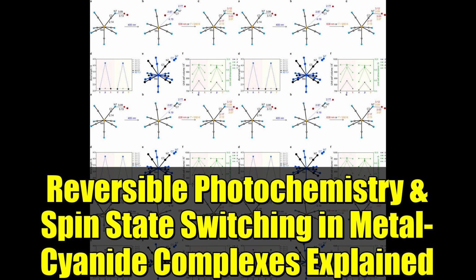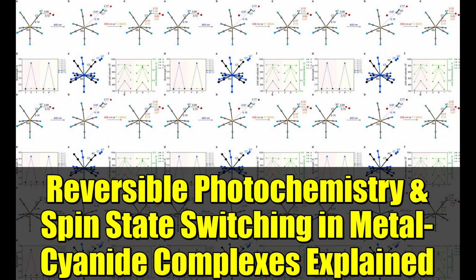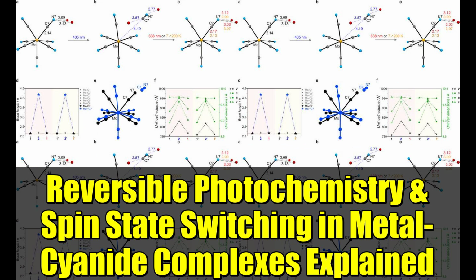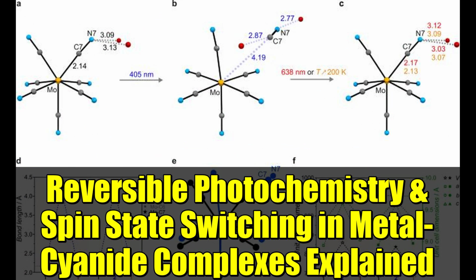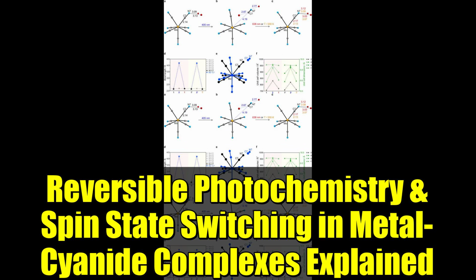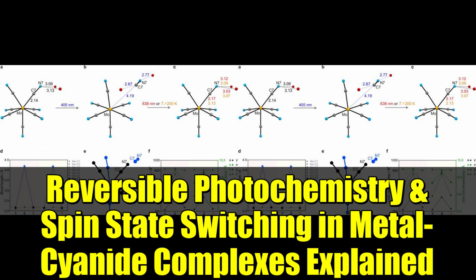The χT profile, recorded in the dark immediately after irradiation, revealed a plateau around 1.84 cm³·K/mol in the 20 to 100 K range, close to 1.875 cm³·K/mol expected for a magnetically isotropic S = 3/2 state. Additionally, the M-H dependence for 2 showed a magnetization close to 3.0 μB at 7 T, indicating a high-spin S = 3/2 configuration, in good agreement with XMCD results and the magnetic data for 3.